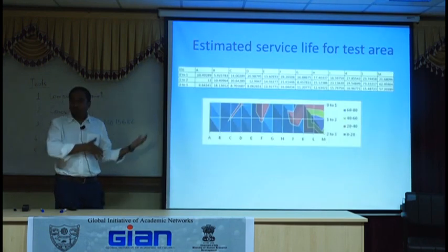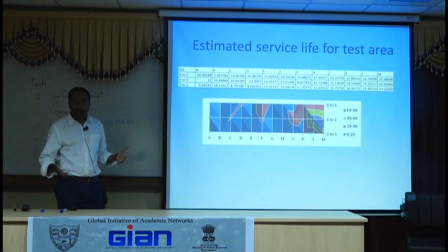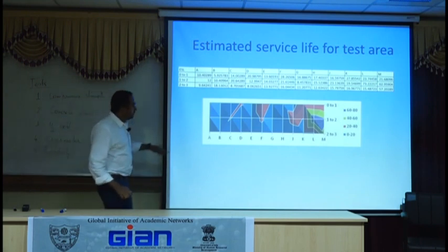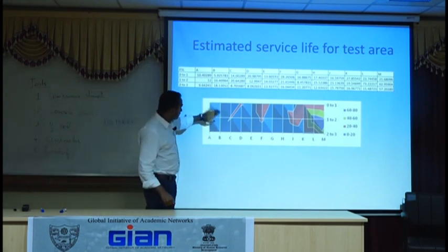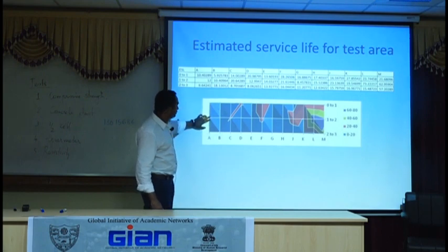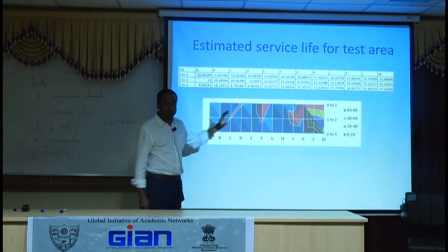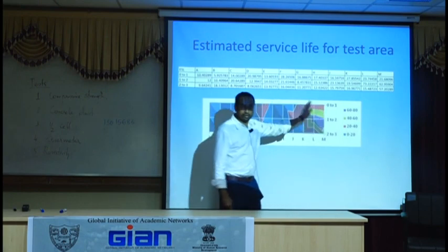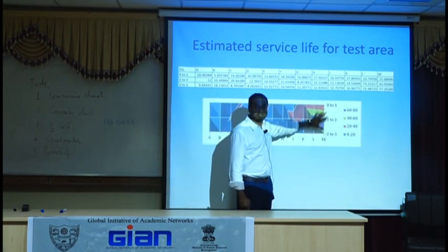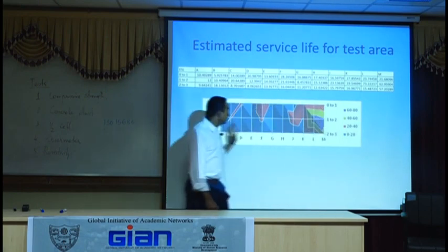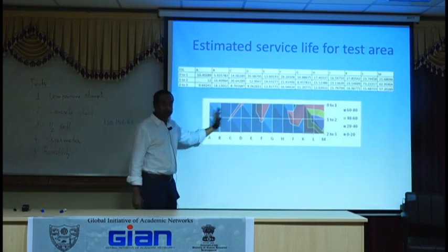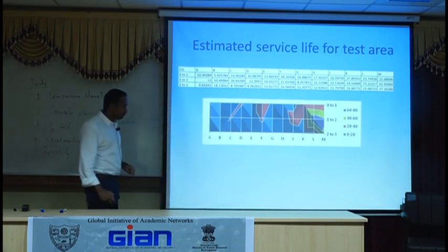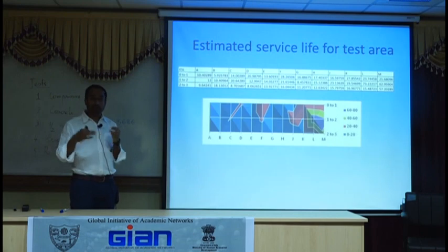And you multiply those two factors. If you have more factors, you can multiply those. And the 12 that you had measured somewhere here, which is 12, will then become the grid. So 12 multiplied by the factors. So you can see over here, you have better service life. I mean, the corrosion is unlikely to initiate here. Corrosion is more or less likely to initiate on this side of the structure. So this is my prediction, okay?